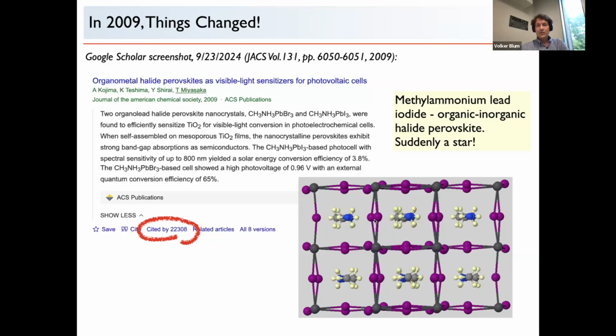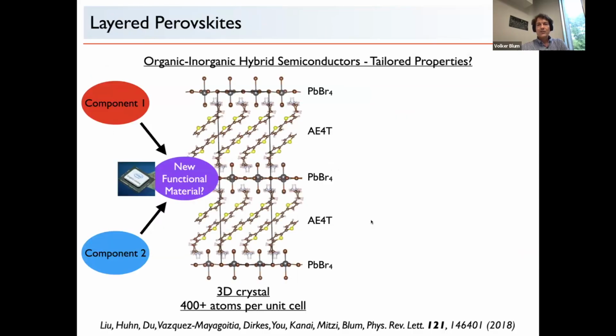For instance, you can have octahedra, but they don't have to be connected at every corner. So you can have a layered perovskite too, like this material here. So here is an inorganic lead bromide layer in this case. You have octahedra, and in between you have relatively complex molecules. And so the rationale behind this